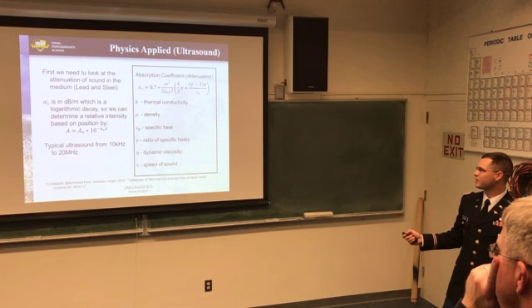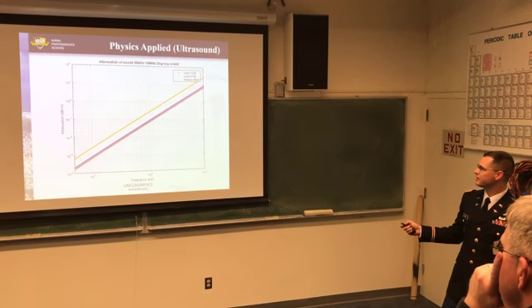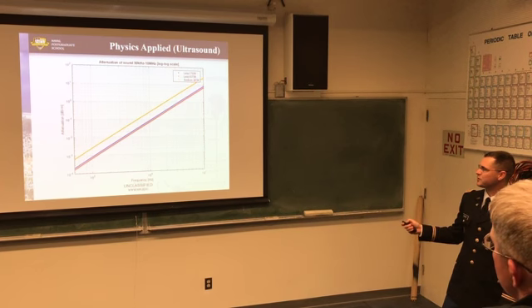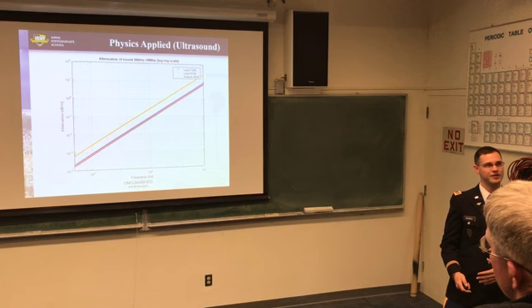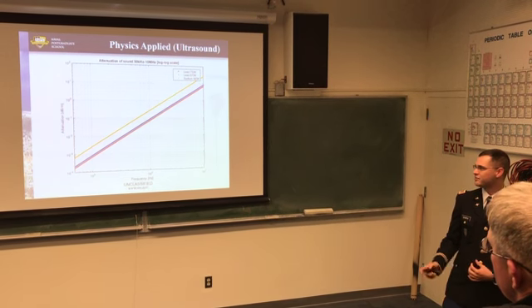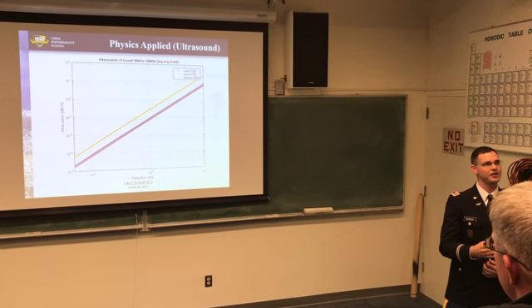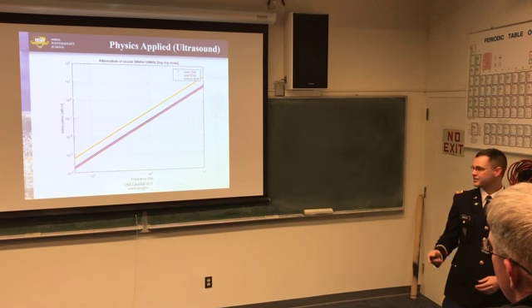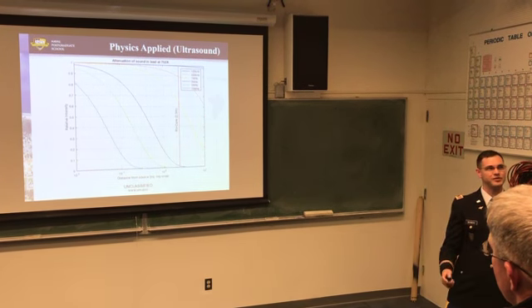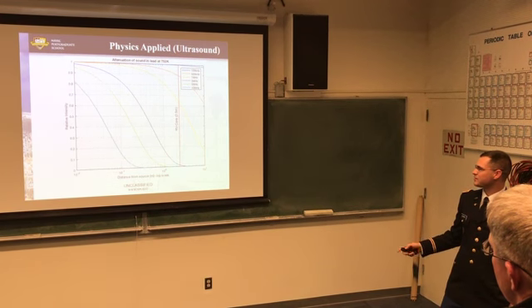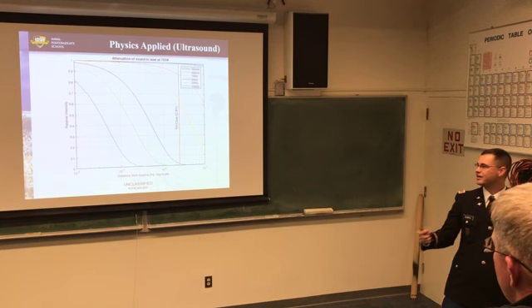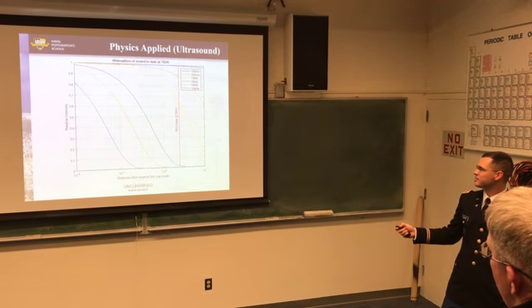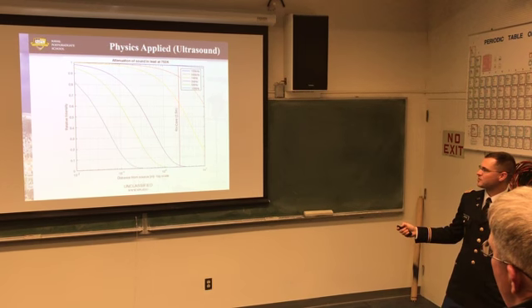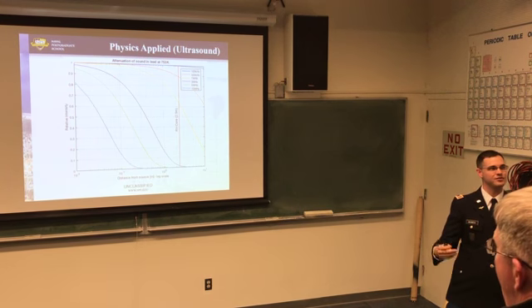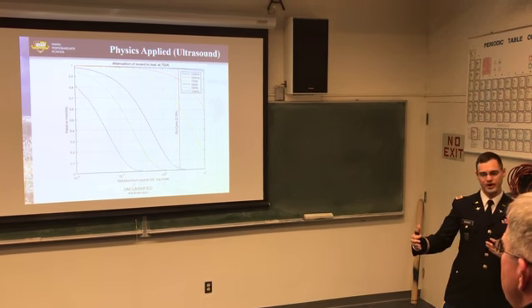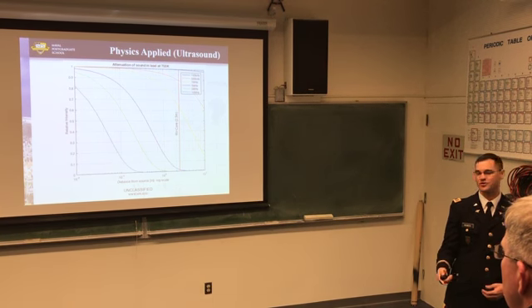So we determined all of those for the upper and lower limits of lead within our reactor. And then for comparison, we determined for sodium because this technology is currently being used in sodium-cooled fast reactors, and found out that lead actually attenuates almost an order of magnitude less than sodium per distance, which is great. So applying that to a range of different frequencies within the ultrasound spectrum, we found that in order to go from the reactor vessel to the core and back, this is just one of the parameters we looked at. So if you wanted to use 1 megahertz as your ultrasound frequency, then it would be about 65% relative intensity is what you would get over that travel distance. So that just gives you a good range of frequencies that you can use in conducting ultrasonic inspections across your reactor.